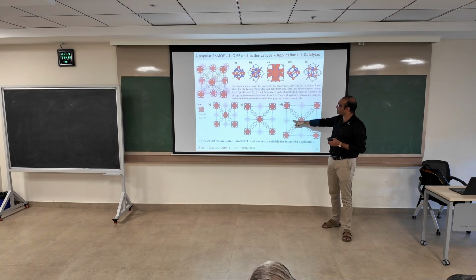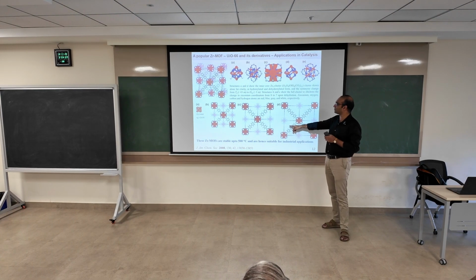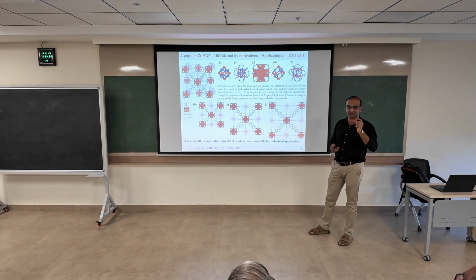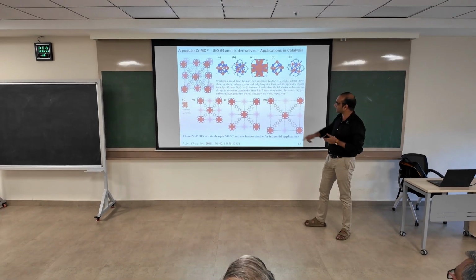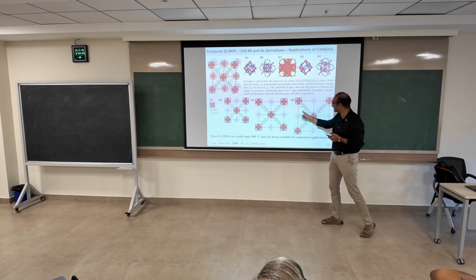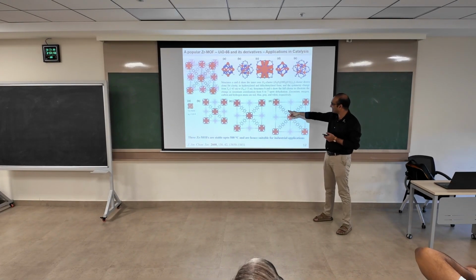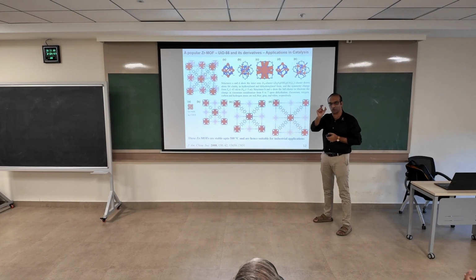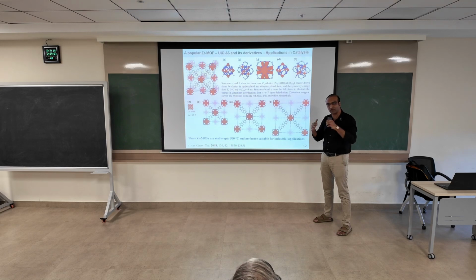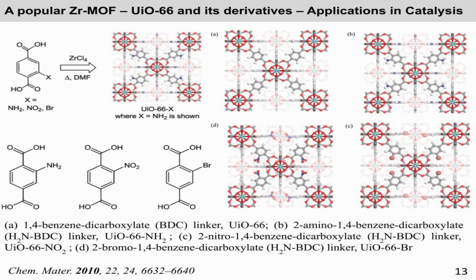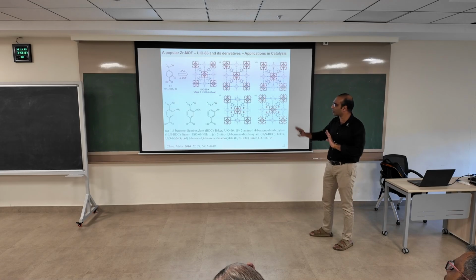Okay, this particular MOF is very good because you have this zirconium oxide linkage, and you can change the length of the linker again, the same thing that we saw earlier. And on these benzene rings, you can have functionalized groups. You can have amine groups or NO2 or something else, so you can coordinate better. Okay, so you can change the linker. You just take the linker, put it in zirconium chloride, heat it in DMF, and you get them.